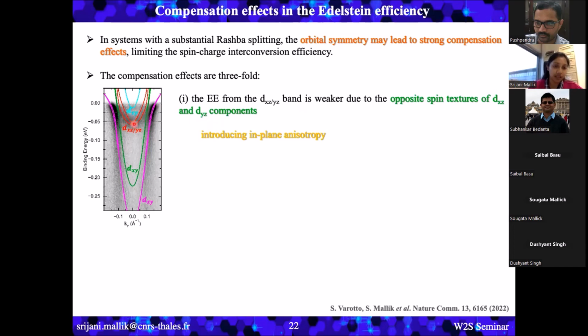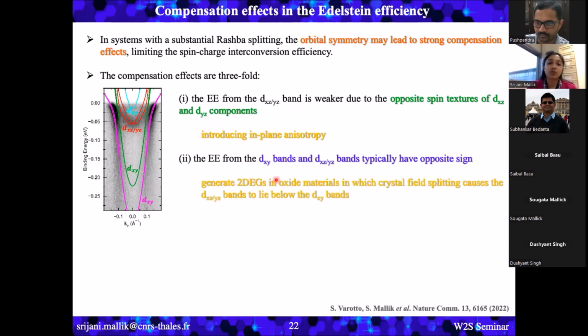The next compensation effect arises due to the opposite sign of the xy bands and the dxz, dyz bands. So for this, what we can do is generate a two-dimensional electron gas in some materials where the crystal field splitting will be exactly opposite. So where basically the dxz, dyz band will lie below the dxy band. If we can design something like this, we can have both similar signs, so we can get rid of this compensation effect.